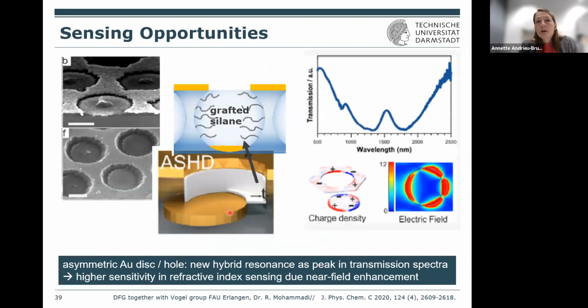And then our project partners investigated this in terms of sensing and different plasmonics. And interestingly, what they found, without going into detail, because that's not too much my expertise, is that there is a plasmon band evolving that's quite sensitive to the silane region, the silica pore wall region here that was functionalized with the ROMP polymer.